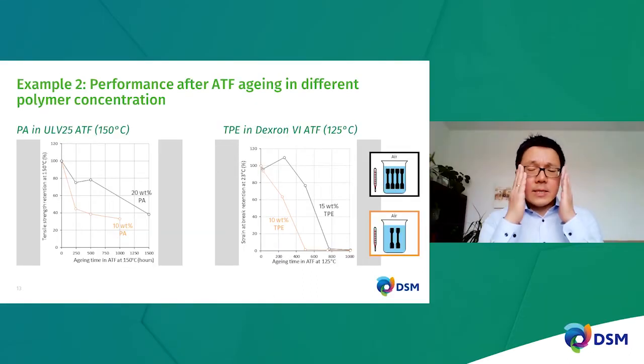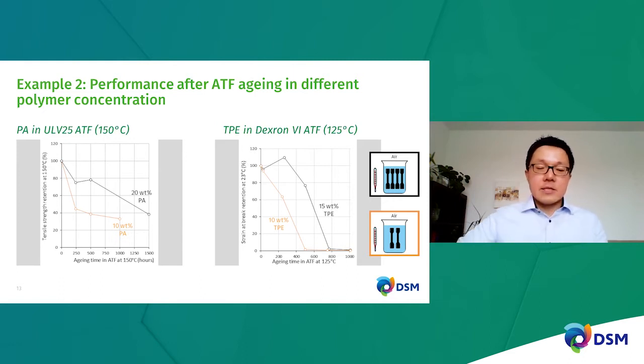Now, one way to understand this is relatively simple. You can imagine that when you start to age polymer in such environments like ATF, as a function of time, there is more and more active species that is generated in ATF that start to attack the polymer. Now, if you have more polymer in the jar, statistically speaking, less active species will be absorbed into the polymer on average per sample. So what you see then is that the samples or the polymer start to be degraded much later when you have much more polymer in the aging jar compared to the situation when you don't have a lot of polymer.